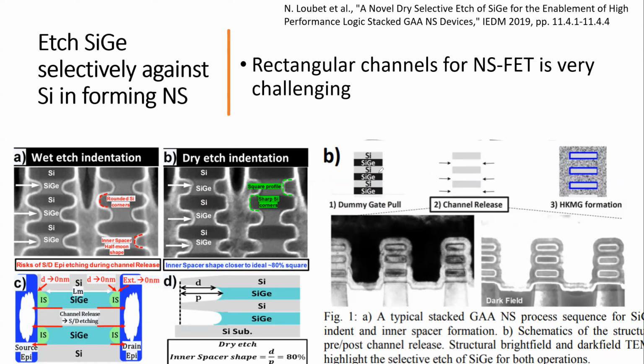But after you form it, you want to create a pouch that is etched in for the inner spacer. All right, here is for the inner spacer. The SiGe here is for the later HKMG process. And then you want to have a rectangular, square profile. You don't want this rounded shape, all right? That's what you don't want.